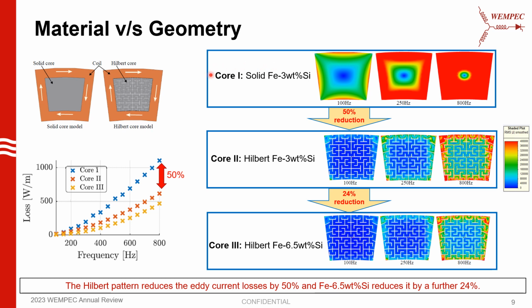To assess the impact of using the high silicon content steel and the Hilbert pattern on the eddy current losses, we performed a set of FEA solves. So we designed three different cores, where the first core is a solid core with a coil wrapped around it. This is exactly a tooth in the stator, with the same dimensions as a tooth with a coil wrapped around it.